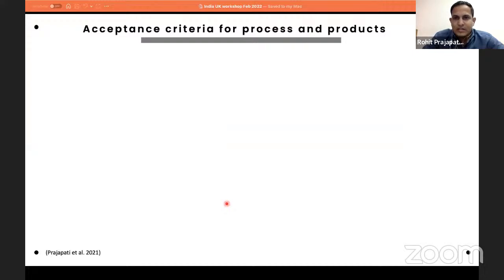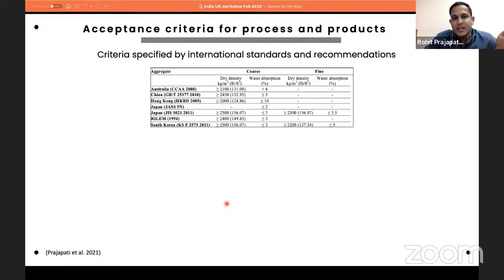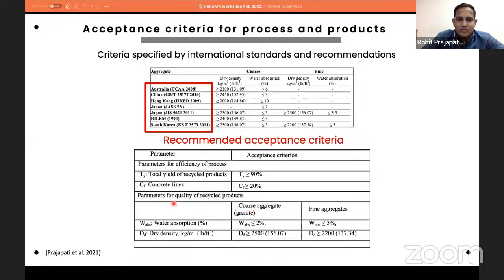So what is the acceptance criteria, or how did we optimize this process? First we set an acceptance criteria for process and products. The process is the thermomechanical beneficiation, and the products are the produced recycled aggregate. We looked at a few stringent standards, and then we pulled out some values for dry density and water absorption, which are the key critical properties for recycled aggregate and have a direct relationship with the amount of adhered mortar on the RCA. From that we got the parameters for quality of recycled products, in terms of water absorption and dry density. And we have 2 parameters for process efficiency, the total yield and the amount of concrete fines.